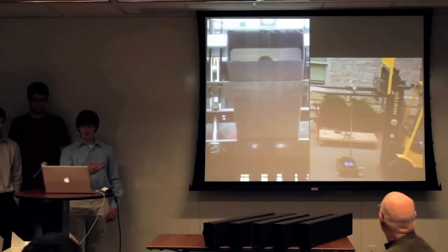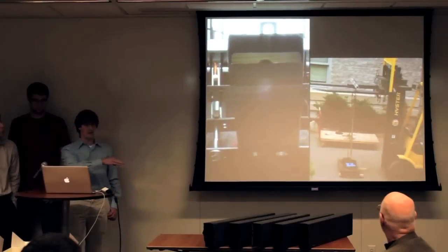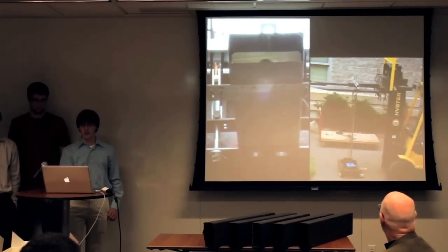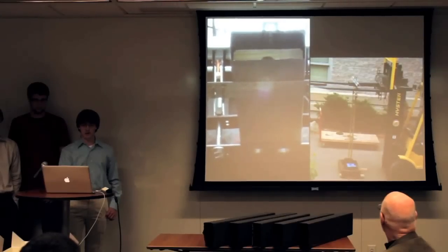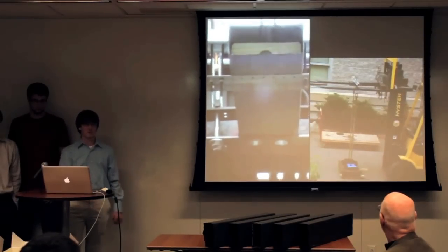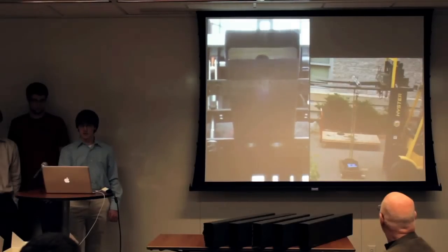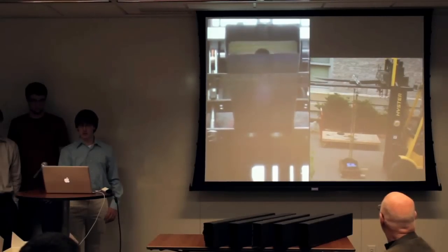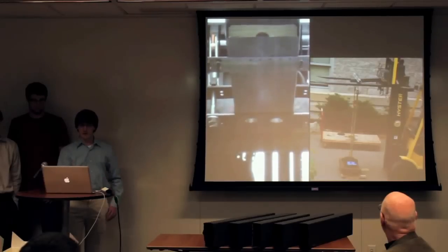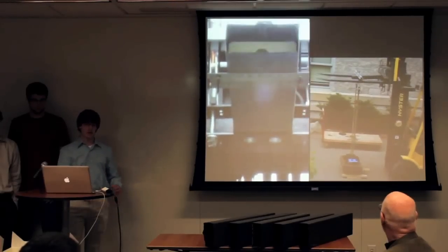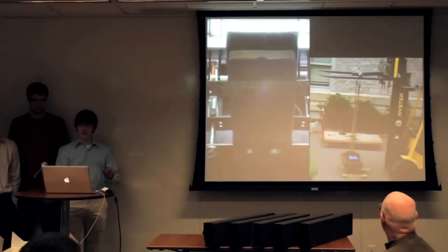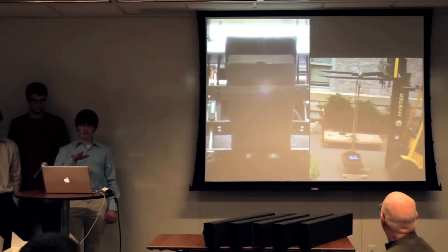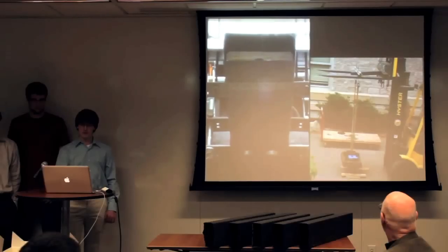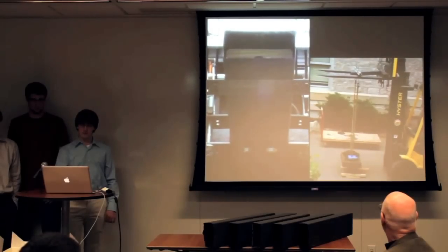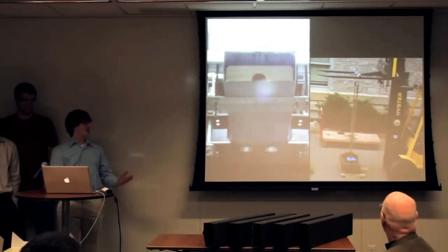Just in case you're wondering, the 2 big plates down there are steel. Each weighs about 250 pounds. And then to get the extra 100 pounds, we had just regular weights from a weight room lying around. So we start to raise it up. You can sort of see the beam bend slightly, and it comes off the ground. And we heard a little bit of cracking, so we decided to let it sit. And then eventually you're going to see it just sort of snap down. That's how it failed.